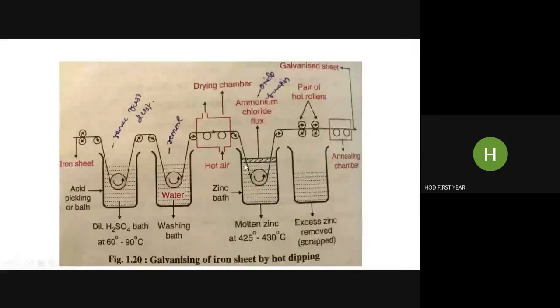Now here that article or sheet gets coated with zinc. It is then taken out and passed between a pair of rollers to get uniform thickness, to remove the excess zinc coat and also to have good adherence, good contact between zinc and the steel sheet. Excess zinc is collected over here and circulated back to the molten zinc tank. Then the coated and pressed sheets are passed into the annealing chamber. Annealing means a heat chamber. Here we will get physical bonding between the zinc coat and iron, and here we have a firm zinc coat on that sheet. Here the process is finished. Here we have galvanized sheet.